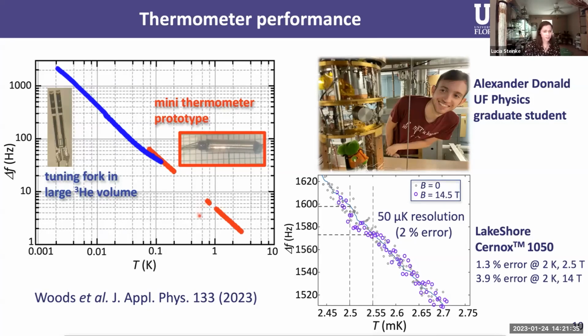Another important characteristic to look at is not only how well can we measure temperature, but also how small a difference in temperature can we resolve. So this is shown here. If you zoom in on part of this curve and just really look at the noise around the curve and project that onto the temperature axis, it gives you an idea of the resolution of this thermometer. And at present, I estimate that in this regime around 2.5 millikelvin, our resolution is around 50 microkelvin, which corresponds to roughly a 2% error.